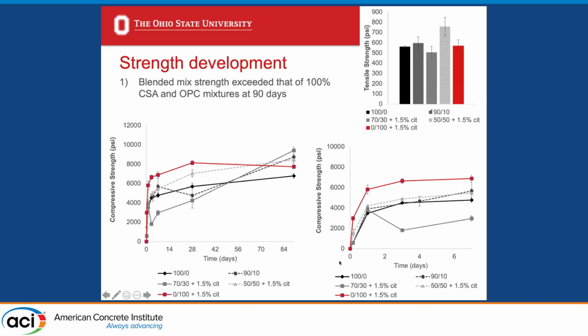However, over the long term, we see sort of a flip-flop in that relationship. Our CSA stops gaining strength at about 28 days and starts to actually lose a little bit of strength or stay pretty consistent. Our OPC continues to gain strength, and our OPC-CSA blends gain quite a bit more strength over that time period. In the end, the blends ended up with strengths between 8,000 and 10,000 PSI, whereas the CSA and the OPC mix were between 6,000 and 8,000 PSI. So there could be some compressive strength gains to be obtained from using these blended materials. And we saw similar performance at 28 days on relative strength of all of these mixtures.